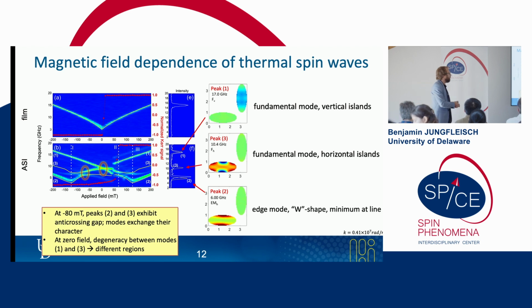Furthermore, we see here at minus 80 millitesla an avoided level crossing where modes 2 and 3 exchange their character. And at 0 field, we see a mode crossing, so modes 1 and 3 are degenerate. The reason for that is that at 0 field, the magnetization in the vertical and in the horizontal elements lies in their easy axis, and therefore the resonance is degenerate.